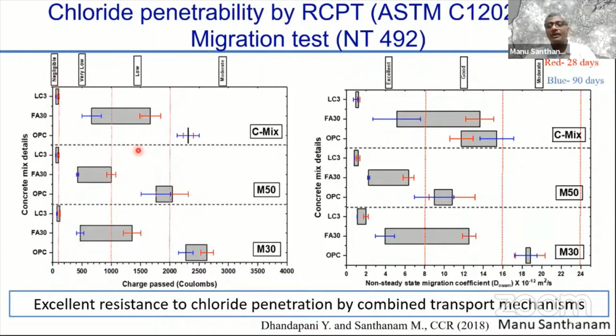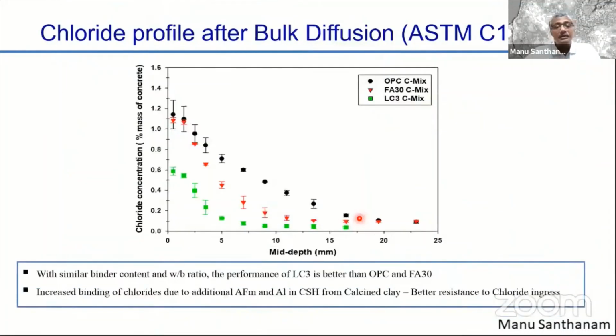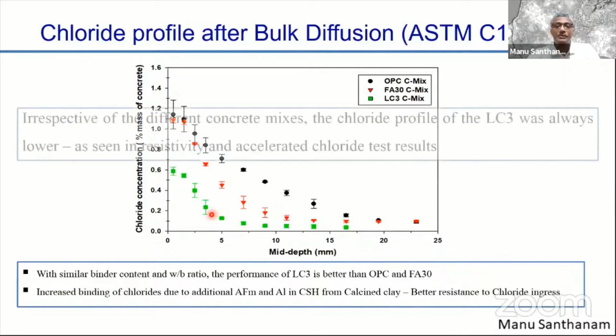If you look at the NT Build test, which looks at the non-steady state migration coefficient, you can see that the LC3 produces the lowest possible non-steady state migration coefficient, which we are accustomed to seeing with silica fume mixes for high performance concrete. That's the kind of level you are actually pushing down your migration coefficient to. In terms of bulk diffusion, again, the result is quite favorable. You see the amount of chlorides penetrating OPC related concrete. Red indicates fly ash concrete and green is LC3 concrete. So you can see that there's a distinct reduction in chloride penetration characteristics also.